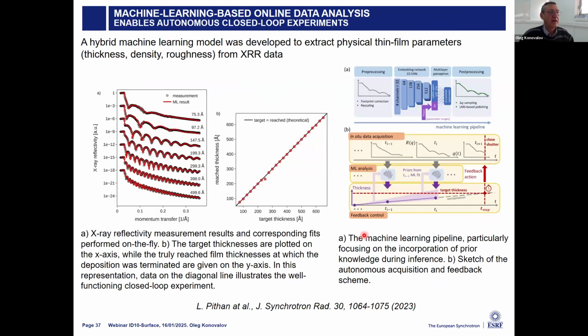And also with the same group, and a bit bigger, we already apply a machine learning algorithm which analyzes the reflectivity curve during the measurements, and during the measurement it can see what the thickness of the film is, and then stop the growth process when we reach the needed thickness. So in principle this can also be applied to get almost instantly the structure from the reflectivity curve after the measurements, already fitted with these deep learning algorithms.